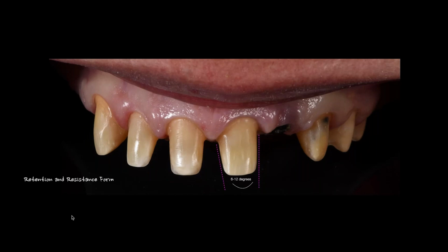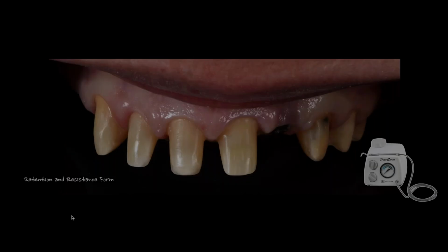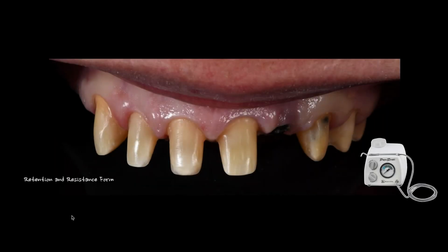So yes, when we're in full coverage, we're still usually going more normal 1.2 to 1.5 restorations, and there are cases where we don't. And when we don't, we're probably going more micro-layered or monolithic materials, which have different challenges to them in the small, thin spaces that we face. So either one of them works. It's really just a matter of getting our parallelism of our preps together, cleanliness of the margin and the cord pack, and managing that tissue.